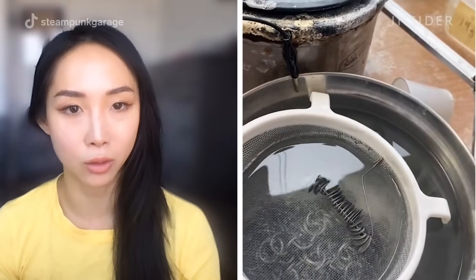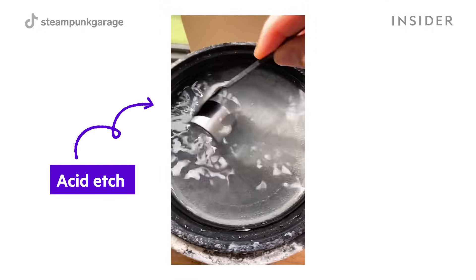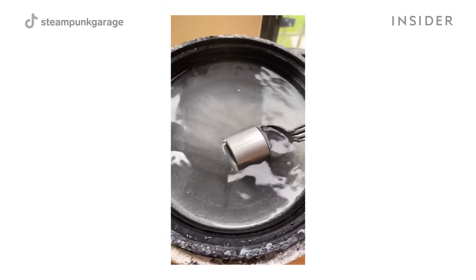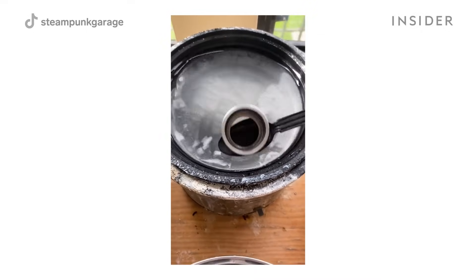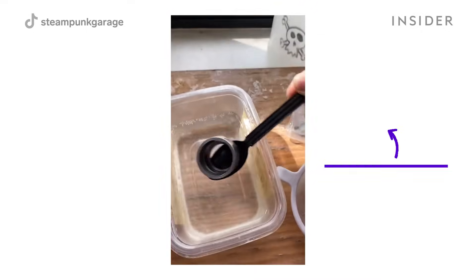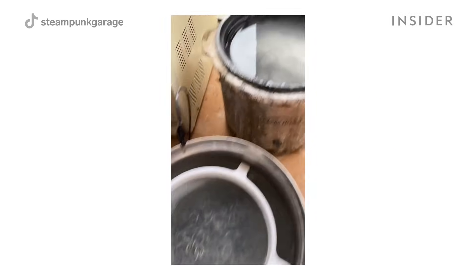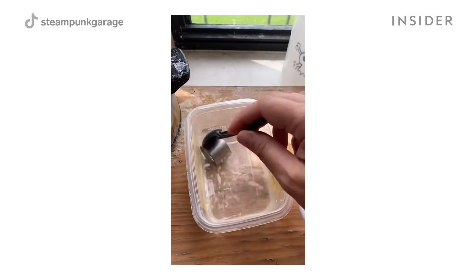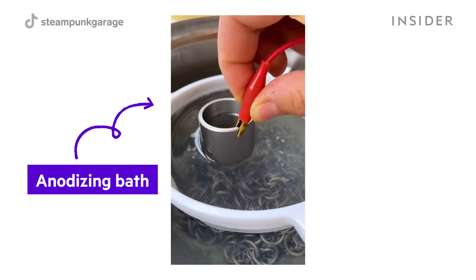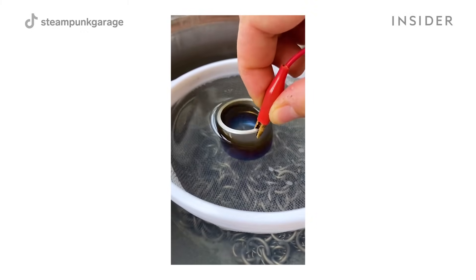In this clip, there are three liquids being used. The first is an acid etch, which strips off the natural layer of oxide that lives on titanium when exposed to air. After that, we rinse it in distilled water — because we don't want to mix the acid and the anodizing bath together, as it would neutralize the agents. Then we move on to the anodizing bath.